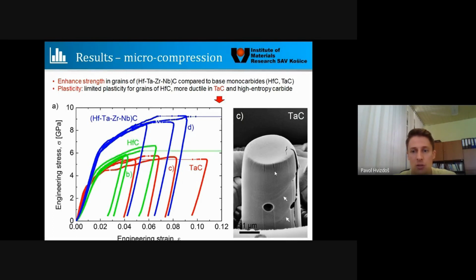bending. So as you can see, there are many slip lines on the surface. We can see cracks, also on top and on the side, but the pillars are still in one piece. So it means tantalum carbide can deform more than hafnium carbide, based on our experience with micropillar compression.